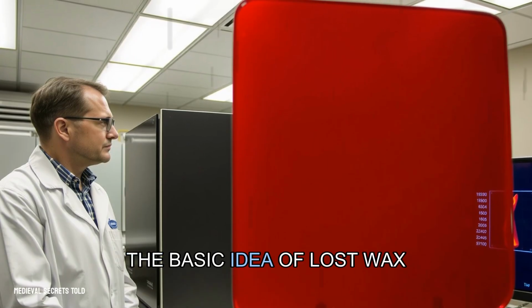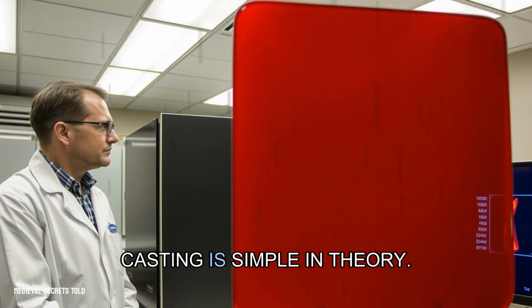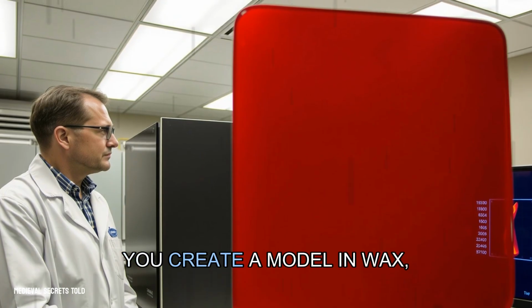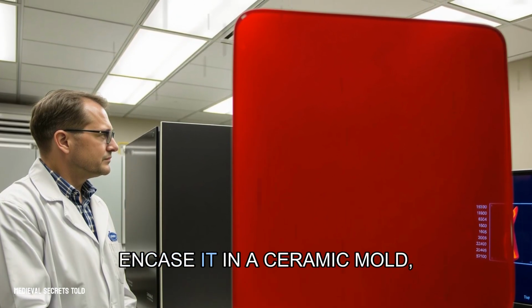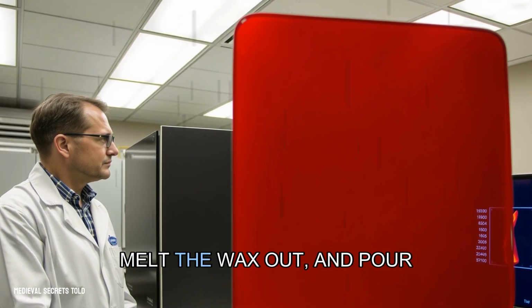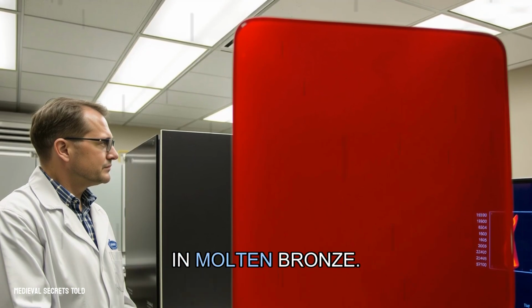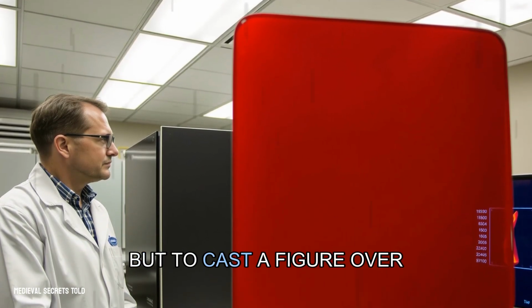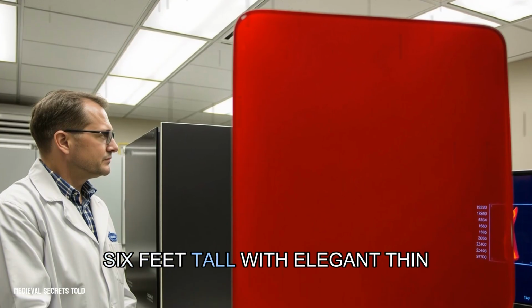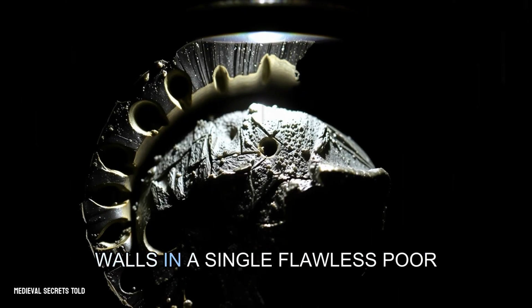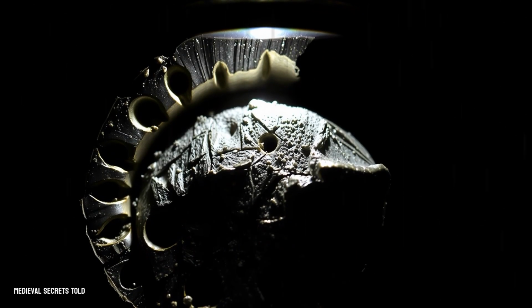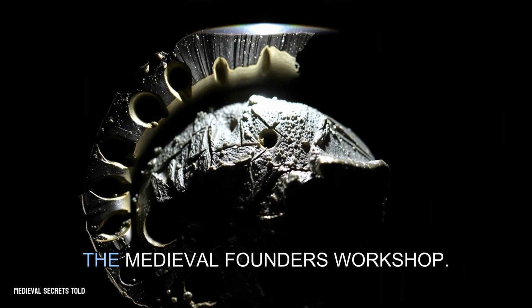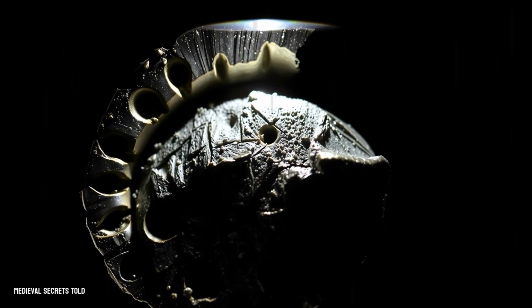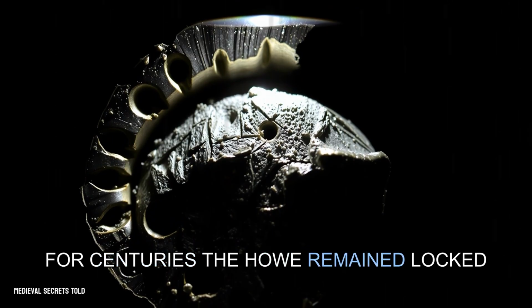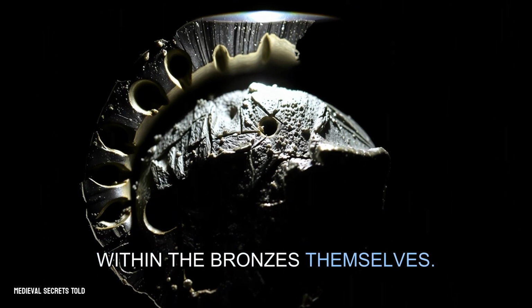The basic idea of lost wax casting is simple in theory. You create a model in wax, encase it in a ceramic mold, melt the wax out, and pour in molten bronze. But to cast a figure over 6 feet tall with elegant, thin walls in a single, flawless pour, that was the guarded mystery of the medieval founder's workshop. For centuries, the how remained locked within the bronzes themselves.